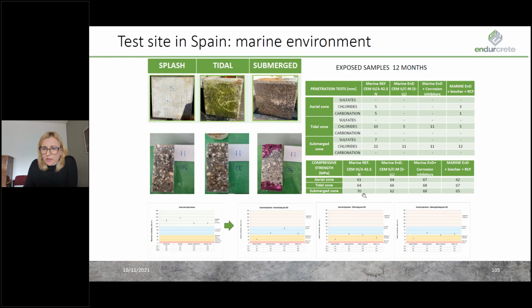As we can see in the compressive strength, actually the EnDurCrete cement or concrete samples were achieving the same or even higher compressive strength compared to the reference one. And as well in the penetration of chlorides and penetration of sulfates, the EnDurCrete concrete samples performed better than the reference concrete. The detailed results of the electrical resistivity were actually presented before by Margarita and Francesca. As we will go further, I will not go into details.